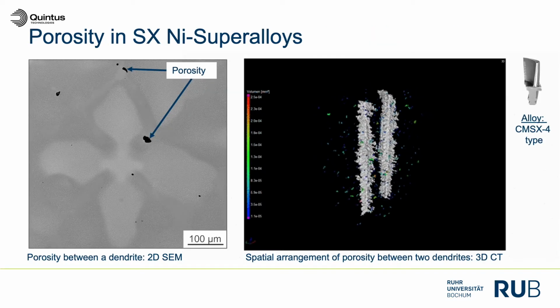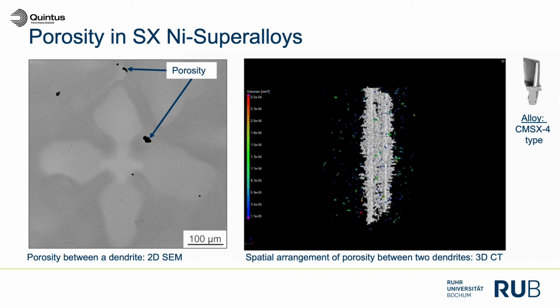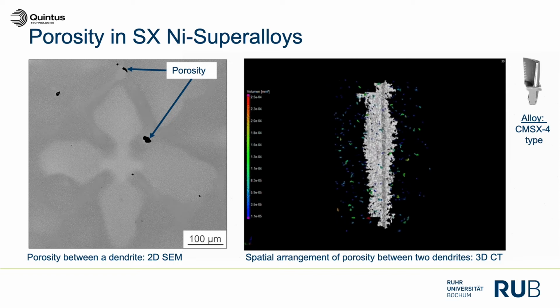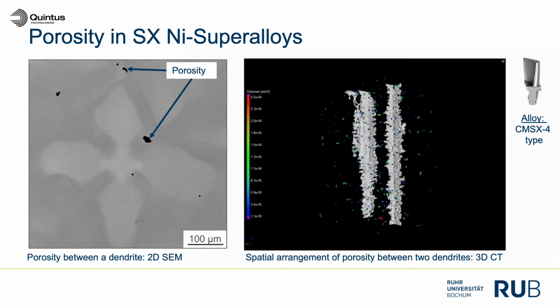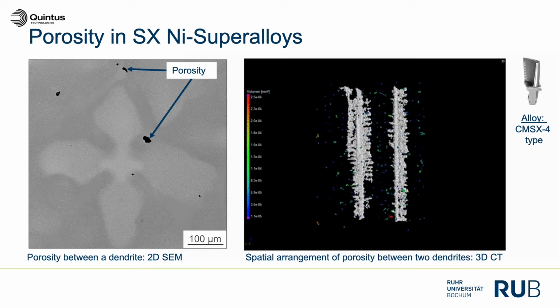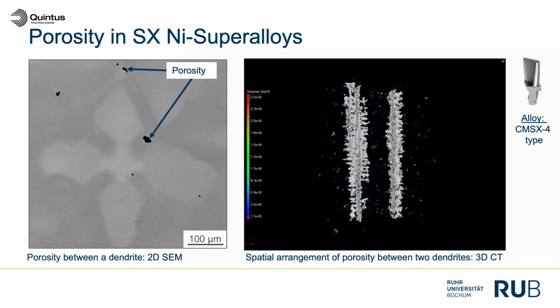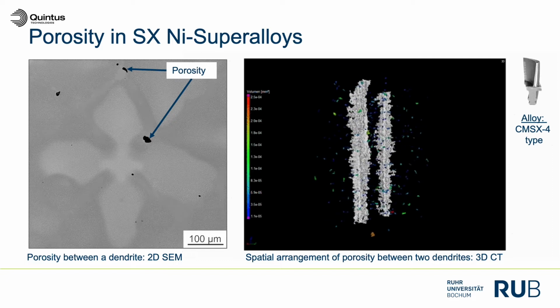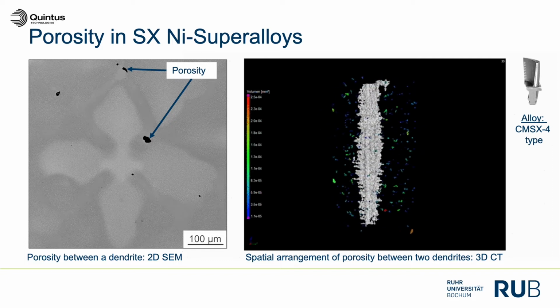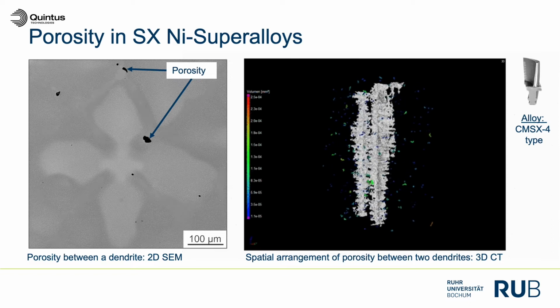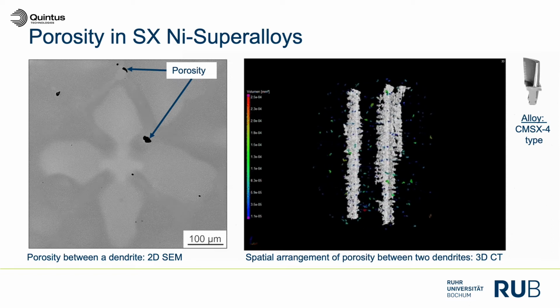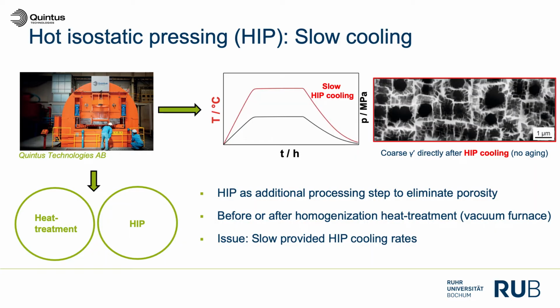So we have a lot of porosity introduced, and this means hot isostatic pressing has to be placed somewhere behind or before the heat treatment. This is an additional processing step, and it costs, of course, a lot of time and money. A very negative aspect of the older HIP units that have been used by the industry in the past is very slow cooling rates. Slow cooling rates are associated with microstructural coarsening, and of course the machine is unproductive when you cool down very slowly.